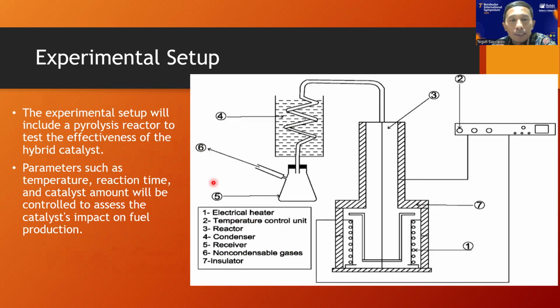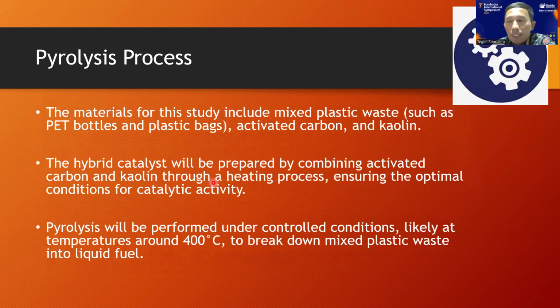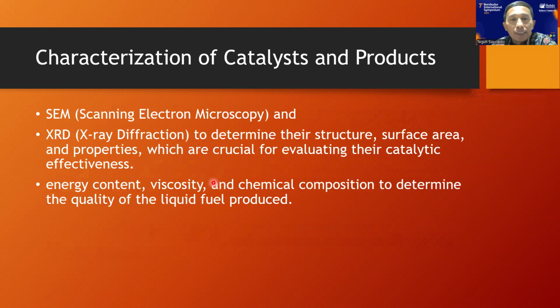This is our experimental setup. We have a reactor, and this is the pyrolysis process. The materials in this study include mixed plastic waste, such as PET bottles or plastic bags, and we are using activated carbon and kaolin as catalysts. The temperature we are using is about 400 Celsius to break down mixed plastic waste into liquid fuels. For characterization, we will use SEM and XRD to determine the surface layer, surface area, and properties. This is crucial for evaluating their catalytic effectiveness.